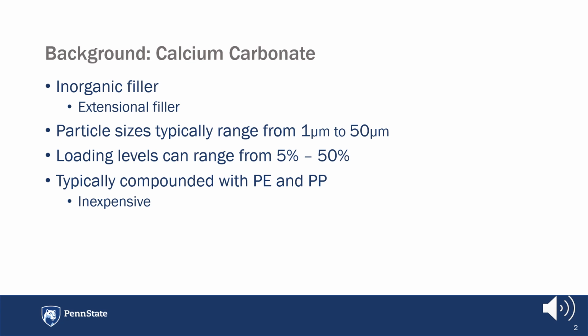Background on calcium carbonate: it is an inorganic filler and is typically used as an extensional filler, meaning it takes up space in the polymer matrix of your material and just adds density to it. Typical particle sizes range from about 1 to 50 microns, and loading levels are around 5 to 50%. It's typically compounded with polyethylene and polypropylene because they're both inexpensive materials. But these two materials aren't compatible for processing, but I will explain that in a later slide.